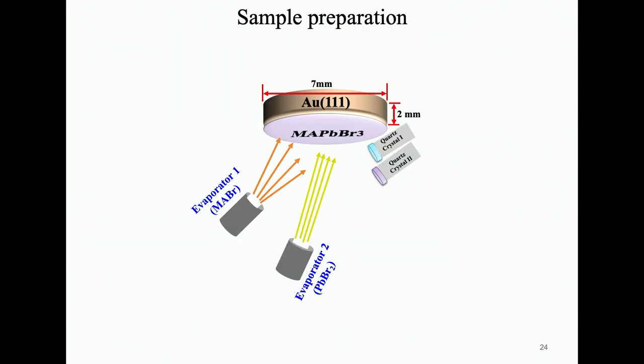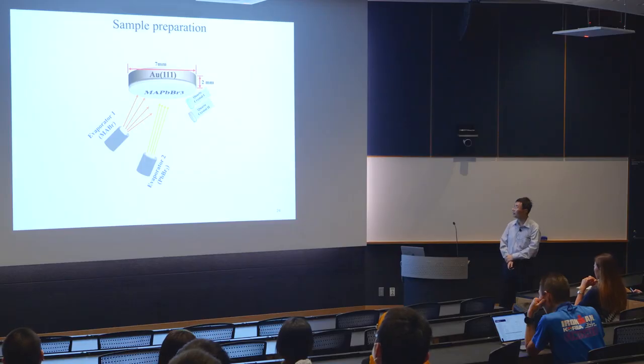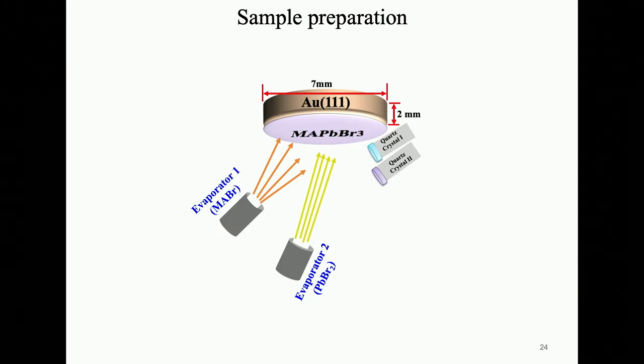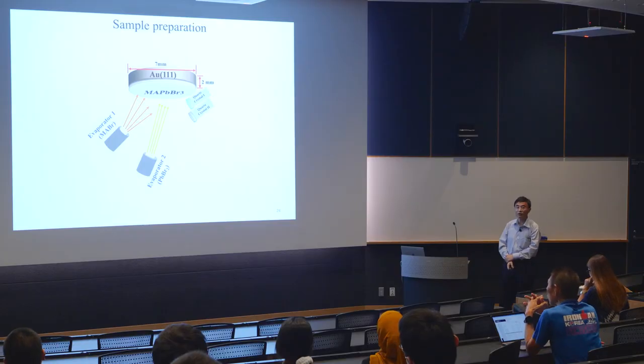For this study, we used two types of sample preparation methods to prepare our samples. The first method is the previously used vacuum cleavage of the perovskite single crystal samples. And the second method is the one shown here. As you can see, it's a dual source co-evaporation method to evaporate two precursors. These two precursors will arrive at the substrate and react with each other to form the perovskite thin film.